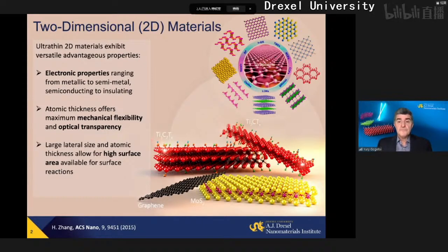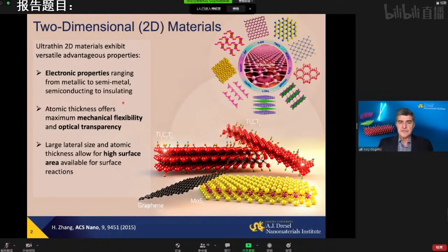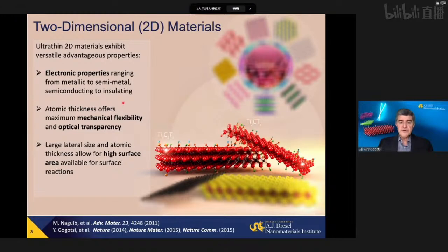And also, by being two-dimensional, they have all their atoms pretty much on the surface. So the entire surface is exposed to the environment. It's available to surface reactions, chemical and electrochemical, whether we're looking for a catalyst, electrocatalyst, or material for energy storage. There is no solid state diffusion required here. And these materials grow in numbers. There are a couple of hundred 2D materials already made.